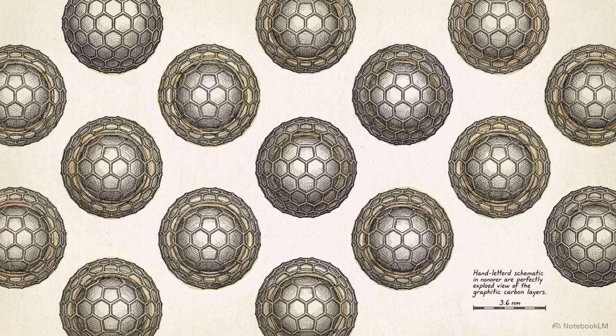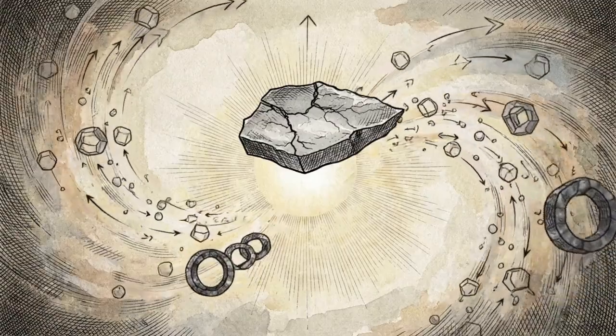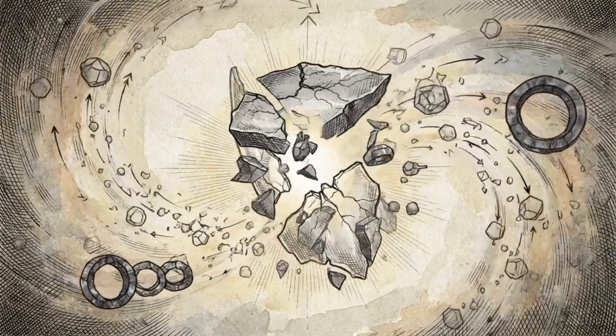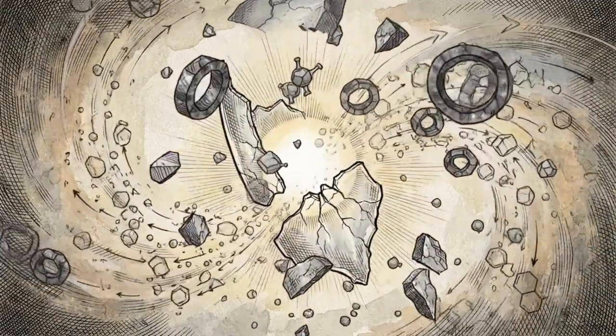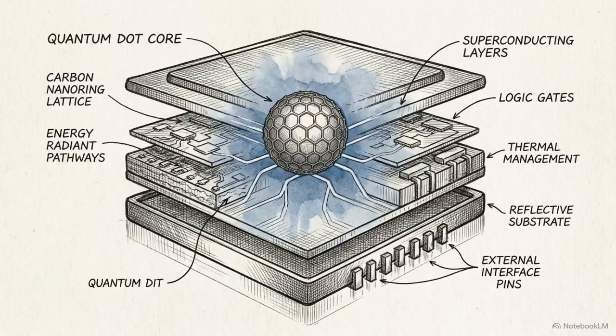This electron microscope image shows the result. The chaotic waste has organized into highly graphitic, perfectly spherical nanoparticles, measuring just 3.6 nanometers across. By tearing the material down to its atomic base and forcing it to rebuild, the researchers have completely erased the plastic's original identity. It is an entirely new, highly functional material.